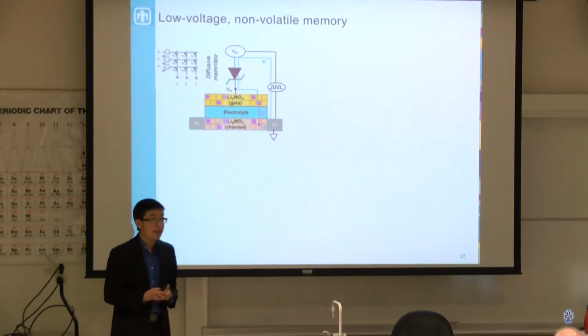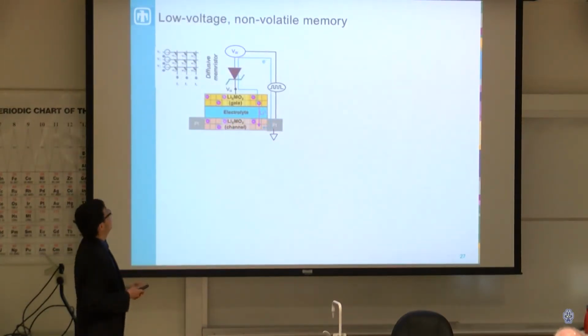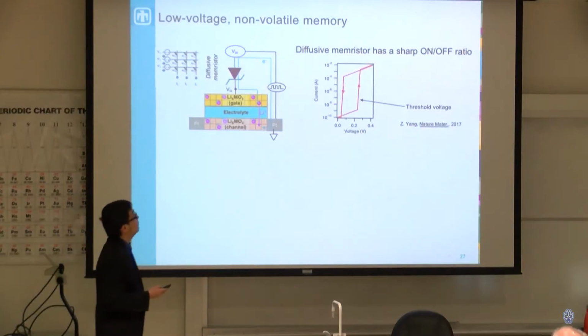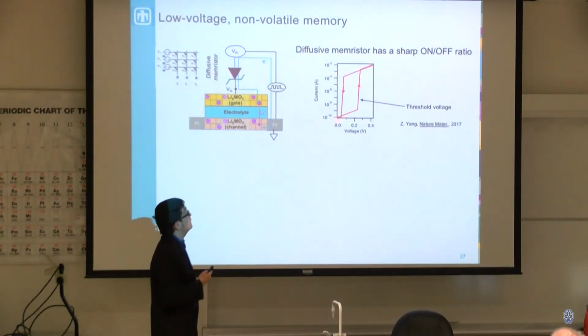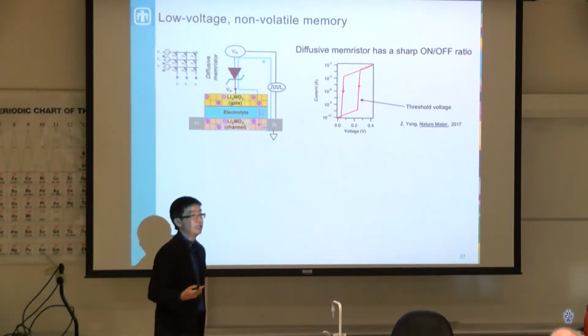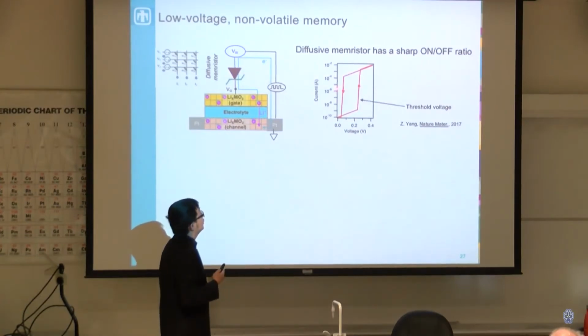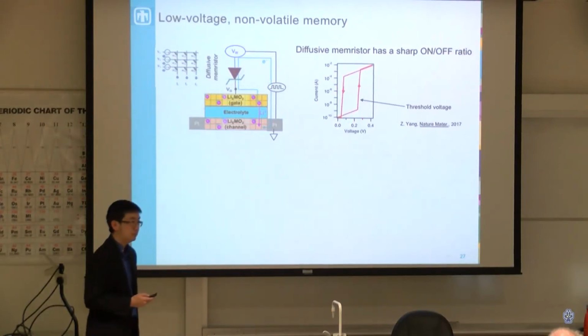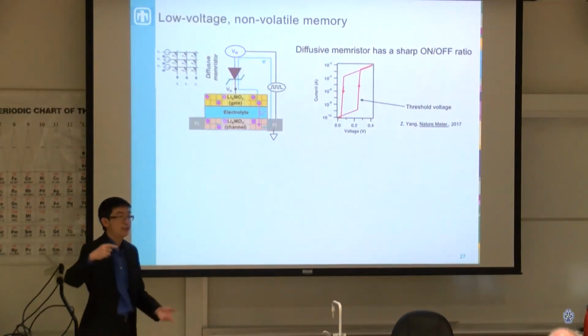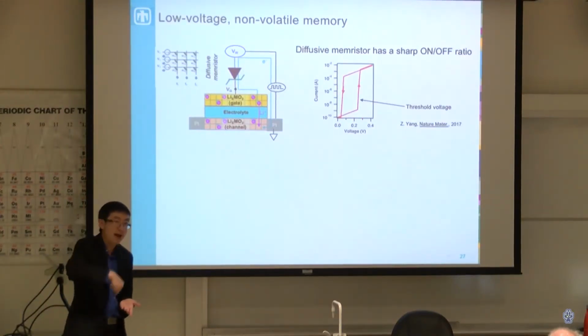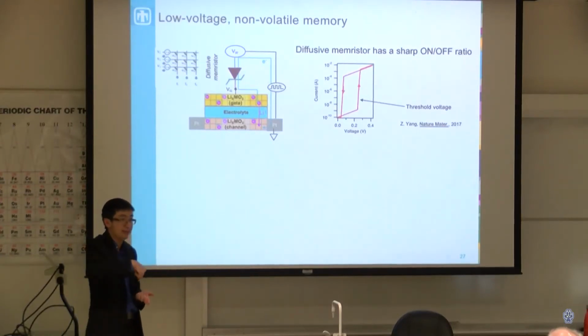So this is an example of what we have done. We use what's called a diffusive memristor, which is an analog switch. Basically, what it means is that when you put a large voltage across it, you're able to change this device from an insulating to a conducting state. So when you put a large voltage, this switch turns on, so you can pass electrons through. And when you apply a little voltage, then this device starts to turn off.